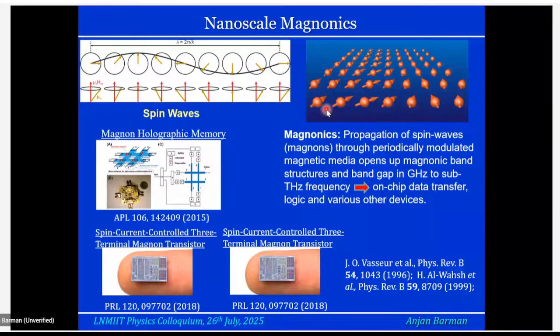So we have a question from the audience. Yes. Manjushree is asking whether spin waves are in the gigahertz frequency range, right? In general, is it only in gigahertz ranges, or do we have other ranges for the spin wave? No, it can go from gigahertz to even terahertz range. For certain materials like antiferromagnets, it can go to a few terahertz frequency range. For ferromagnets, it is usually in gigahertz to hundreds of gigahertz. And it depends on many factors like applied magnetic field, magnetic anisotropy, internal field, and so on.